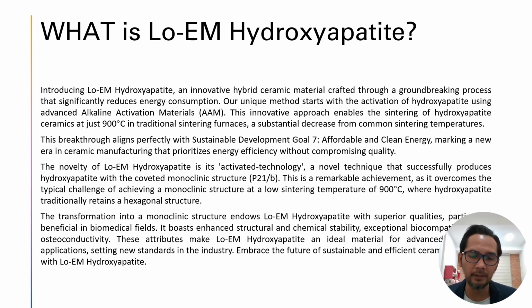Okay, so this breakthrough aligns perfectly with Sustainable Development Goal number 7, affordable and clean energy, marking a new era in ceramic manufacturing that prioritizes energy efficiency without compromising the quality. So the novelty of Lo-EM hydroxyapatite is its activation technology, as I mentioned before, that we use metakaolin for this project to activate the hydroxyapatite mixed with the alkaline activators. A novel technique that successfully produced hydroxyapatite with the coveted monoclinic structure. This is a remarkable achievement as it overcomes the typical challenge of achieving monoclinic structure at a low sintering temperature of 900 degrees Celsius, where hydroxyapatite traditionally retains a hexagonal structure.